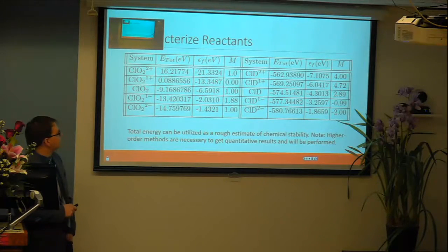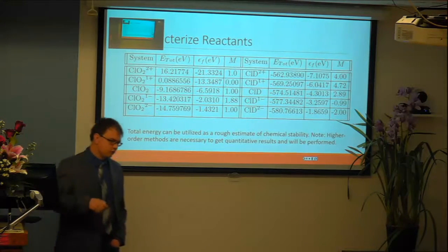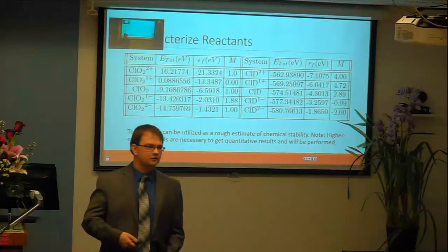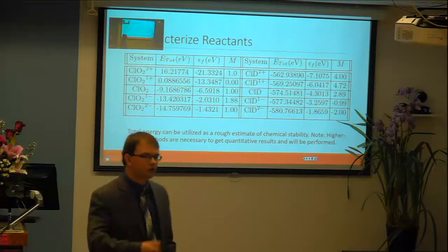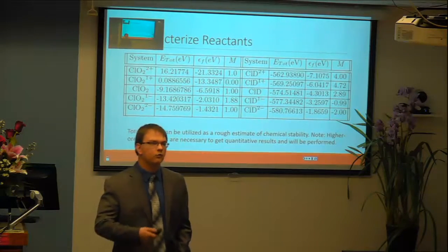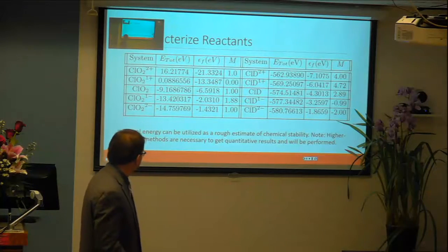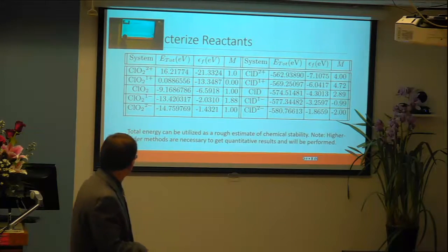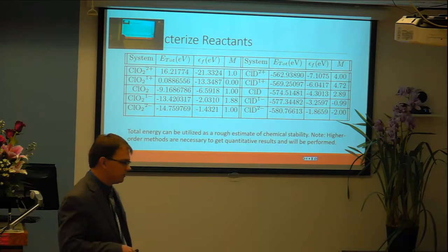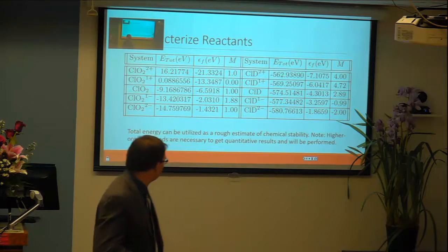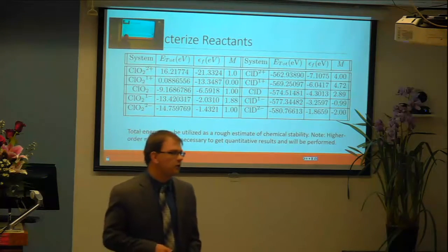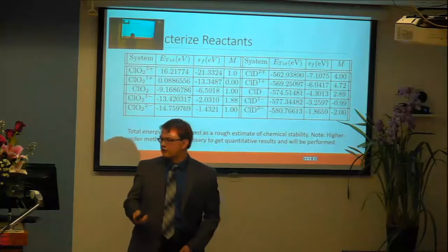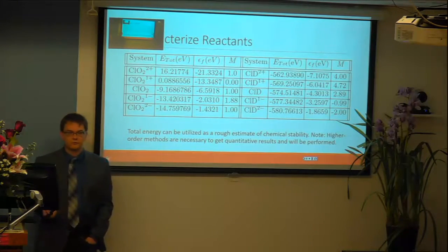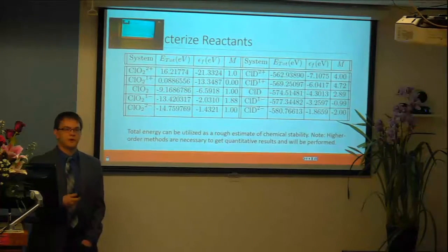So if you look at the total energies, which is most important here, chlorite likes negative charges. So the negative total energy implies that it's a more stable structure, of course, and so if you have more negative, it's implied that it's a more stable structure. Like I said earlier, chlorite is known to be in a single anionic form usually, but as you can see, it's not the lowest number here. This could be an artifact of the results from the DFT. We could move to higher level results, and this may change.